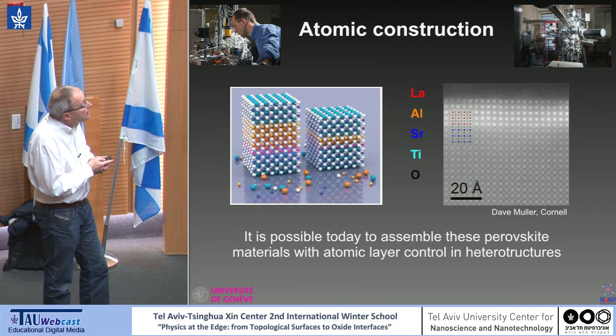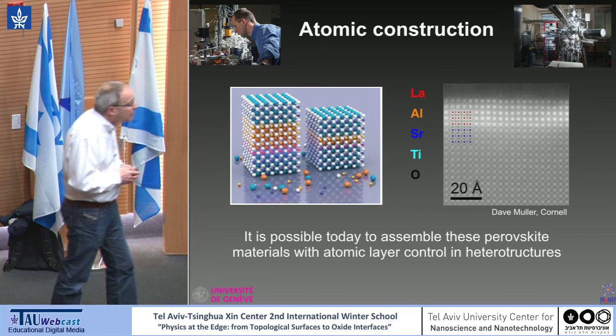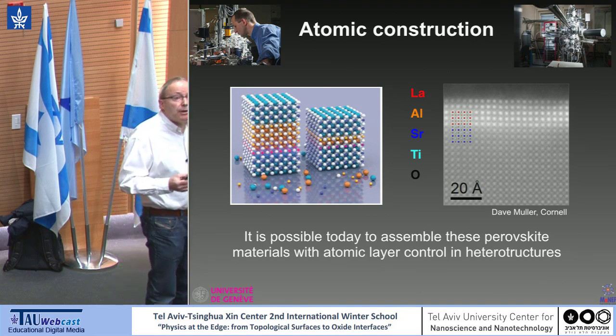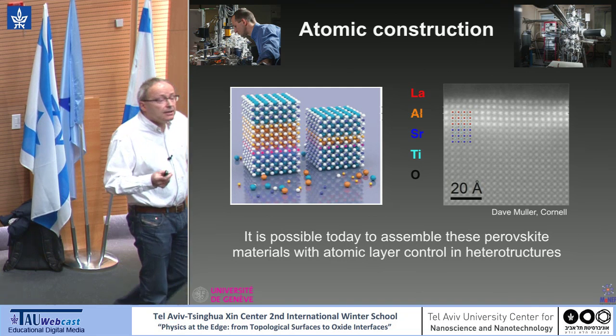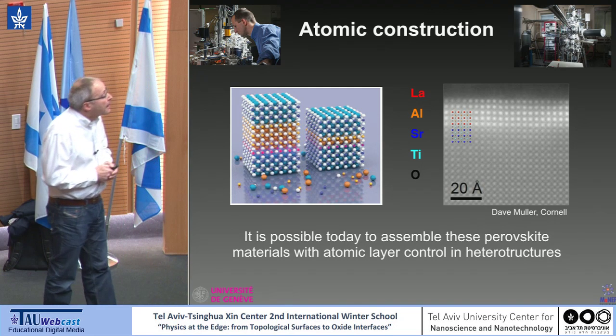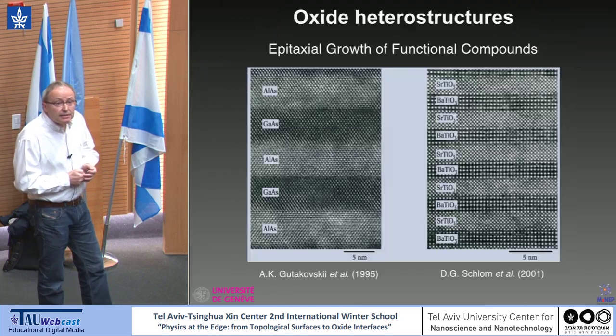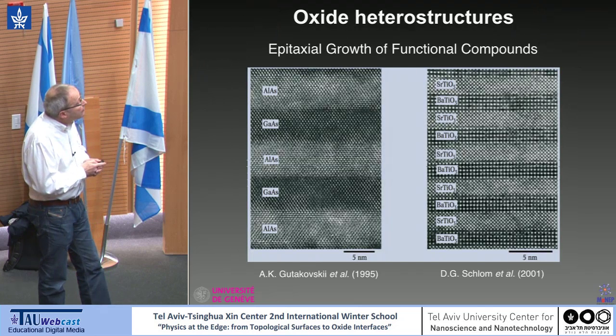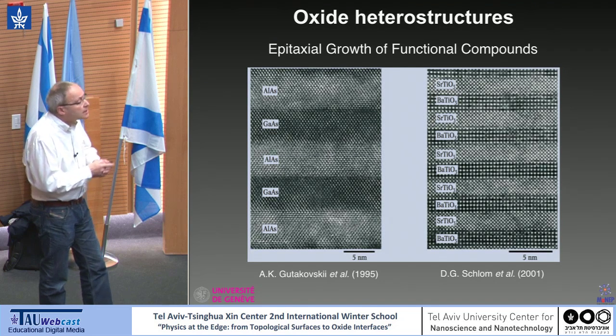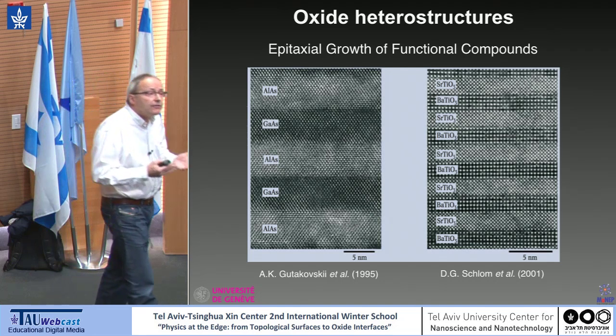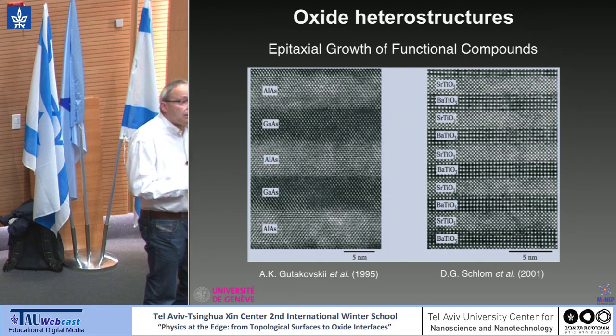And you see here the interface between strontium titanate and lanthanum aluminate. These techniques include pulsed laser deposition, sputtering, and molecular beam epitaxy. And I think it's fair to say today that if you compare III-V structures with oxide structures, the level of quality of the oxide is really becoming better and better.